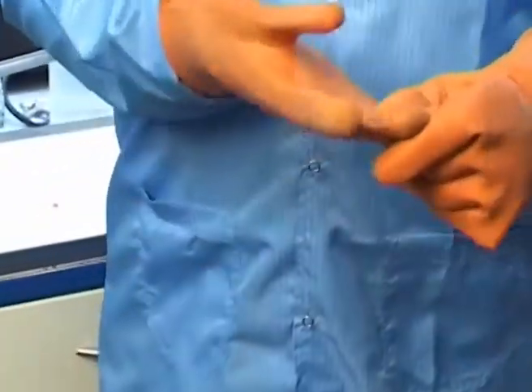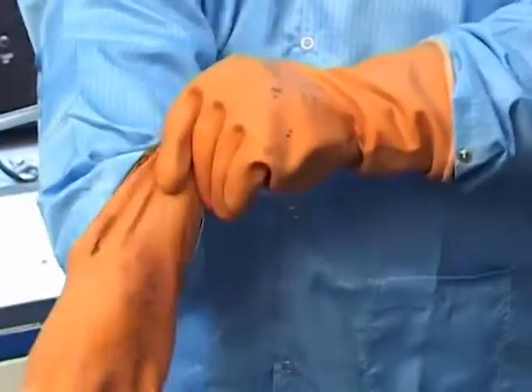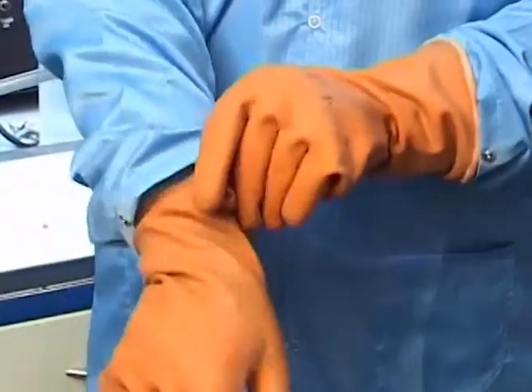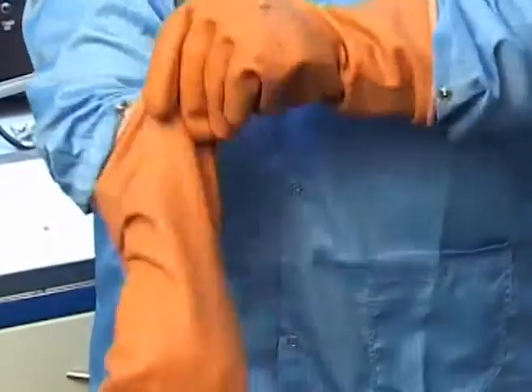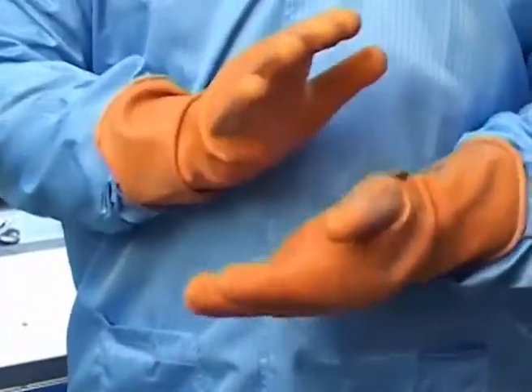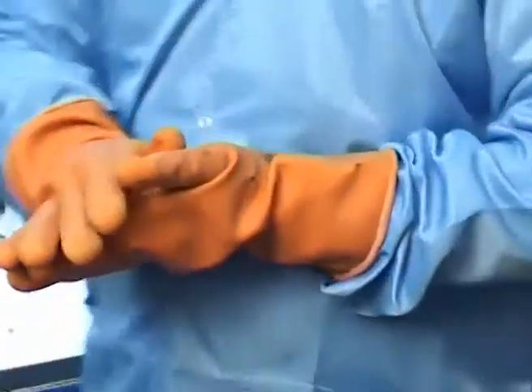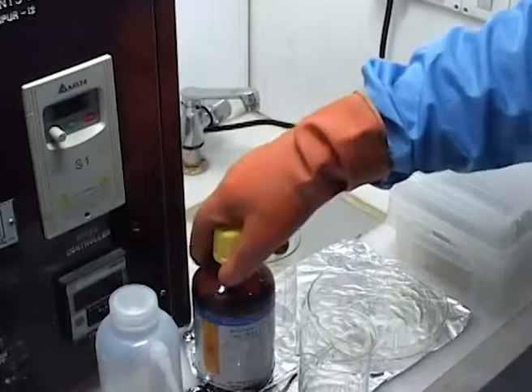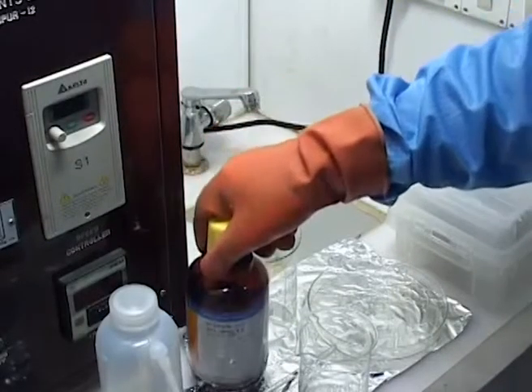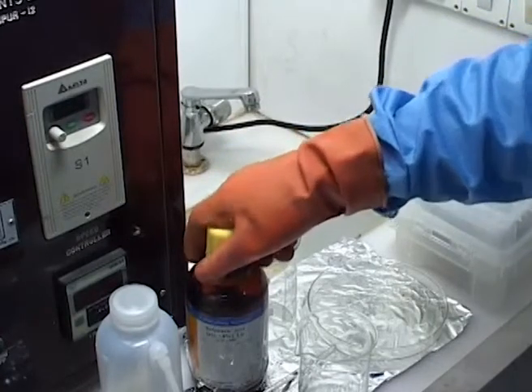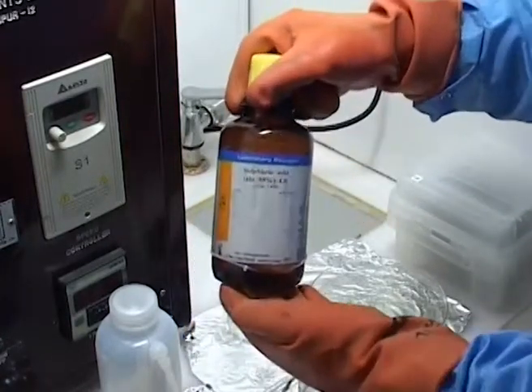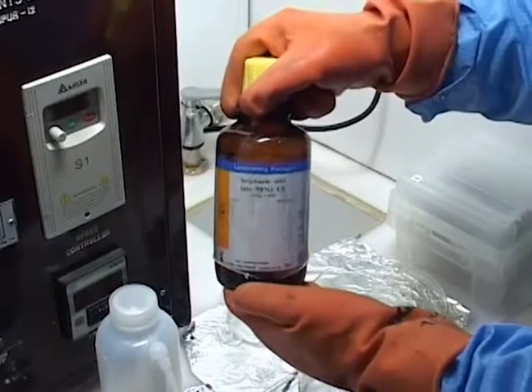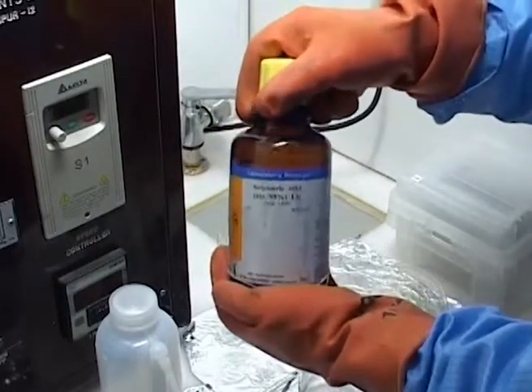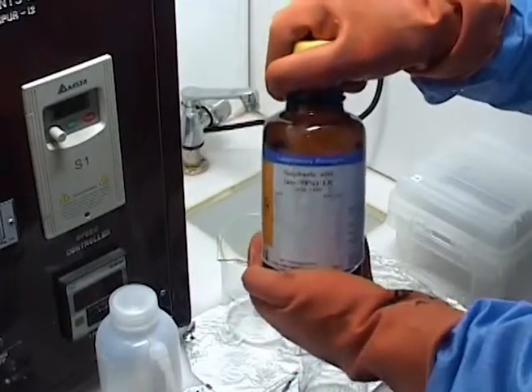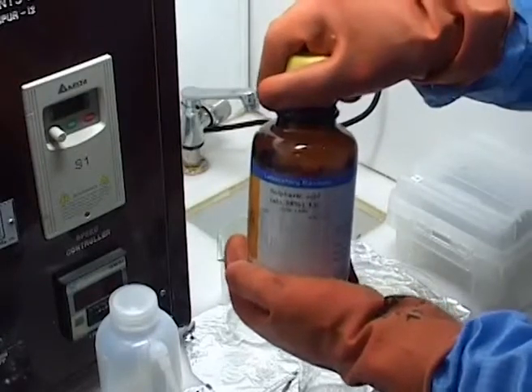As you see here, you can just wear it over the secondary gloves that you are already wearing, which are clean gloves for doing processing. Once this is worn, we are almost ready for preparing the Piranha solution. So what we do is basically pour about, in this case, about 90 ml of sulfuric acid, 98%. As you can see, this is a very, very dangerous chemical, and it has to be very carefully used. And then we'll mix about 30 ml of hydrogen peroxide.